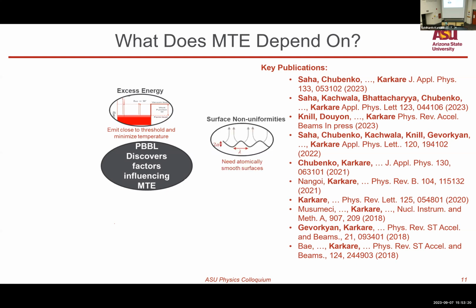One of the most important ones then is the surface non-uniformities. If you have physical undulations on the surface, the accelerating electric field tends to bend and it gets a transverse component, which gives transverse kicks to the electrons. Secondly, if your work function over the surface is not uniform, you have a patch of some random contaminant stuck to your surface, even if they're at the atomic scale, they change the work function dramatically. And you can have patches of different work function that creates transverse electric fields, again, increasing the mean transverse energy. So to really minimize mean transverse energy, you need the smoothest possible surfaces, really atomically ordered surfaces.